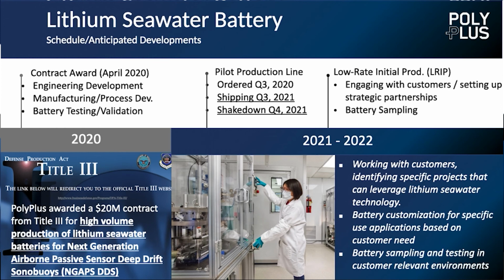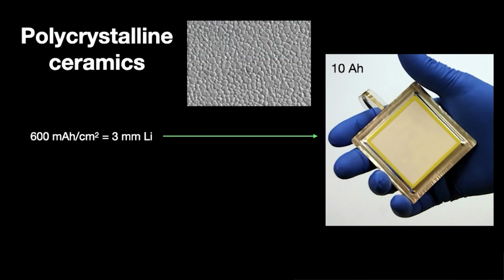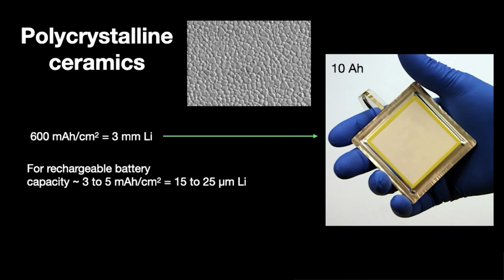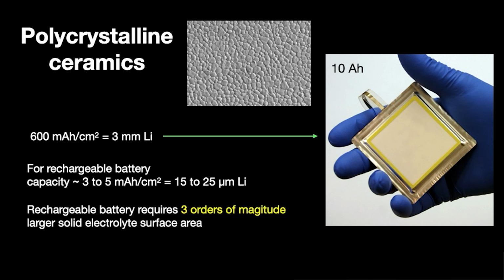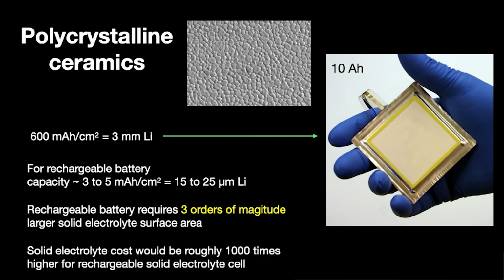So let's get back to this idea of which solid electrolyte we're going to choose for a particular application. As I mentioned, in the seawater battery, we have very high capacity density. When we move to rechargeable batteries, the capacity of the positive electrode is typically in the 3 to 5 milliamp hours per centimeter squared. That's a very different domain. It means that a rechargeable battery will require 3 orders of magnitude more surface area than what we're doing in, for instance, our lithium water battery. So the solid electrolyte would then be 1,000 times more expensive. For us, that would be a showstopper, which is why, as we moved in the development path for rechargeables, we took a different path.